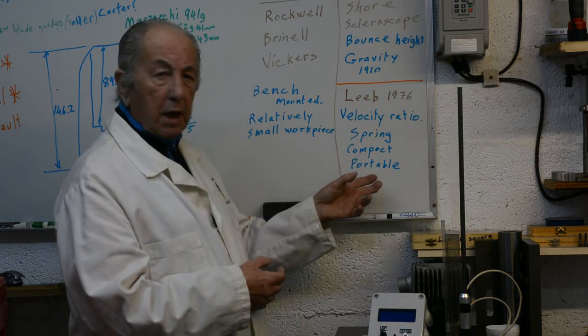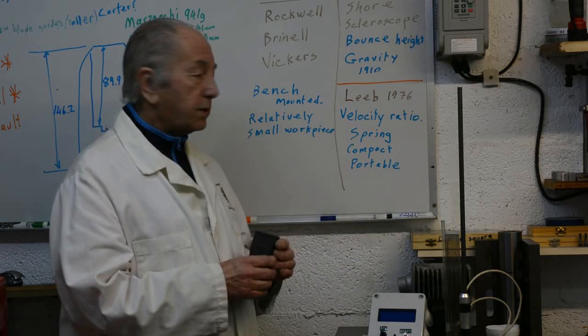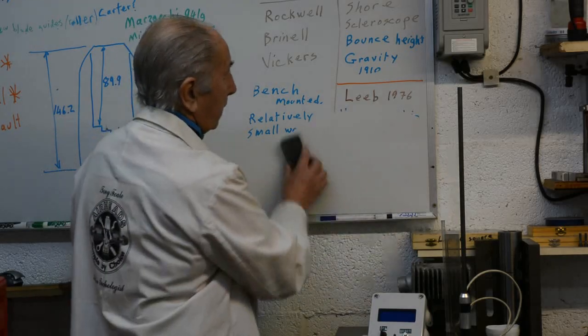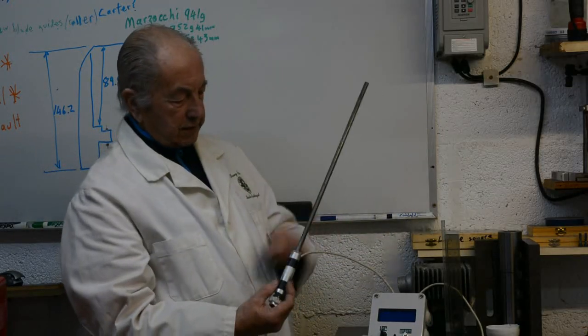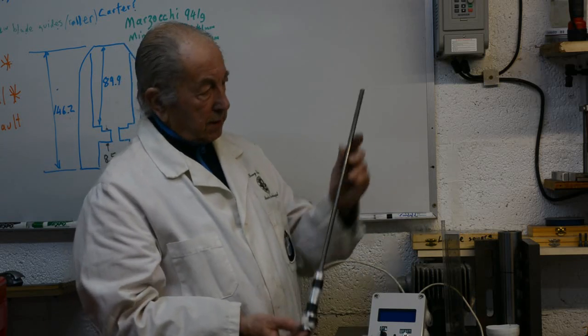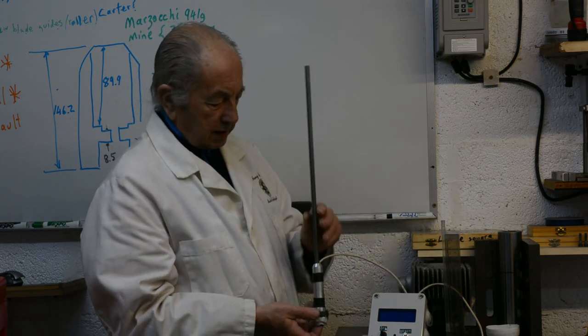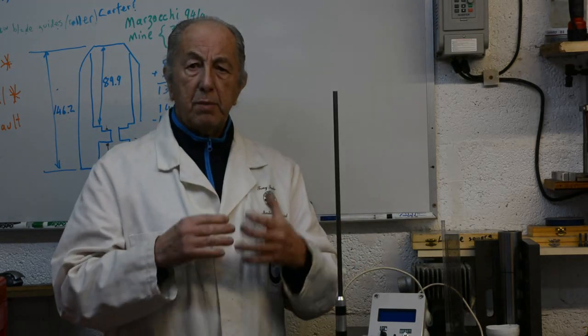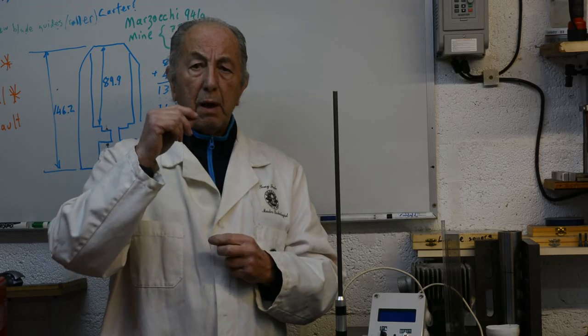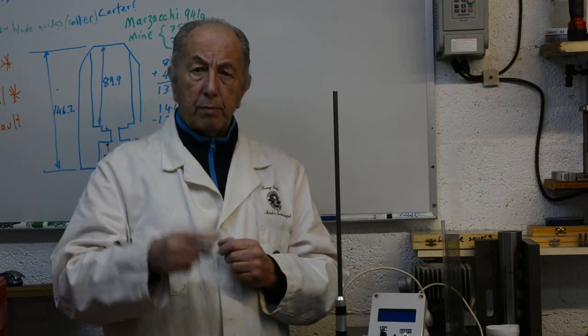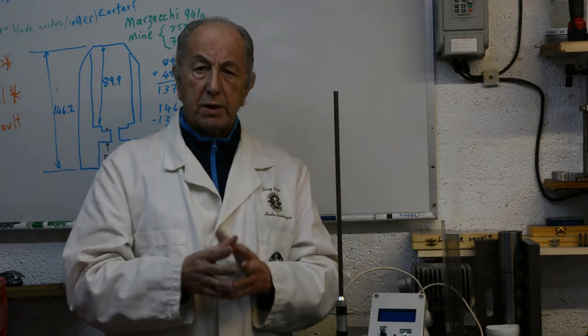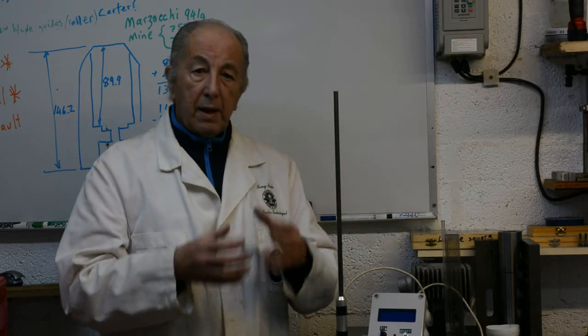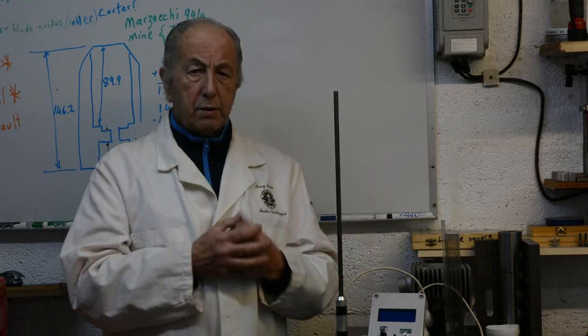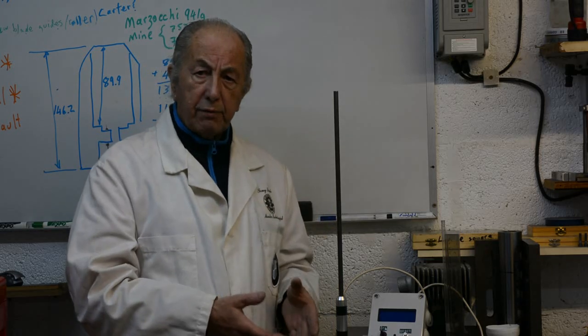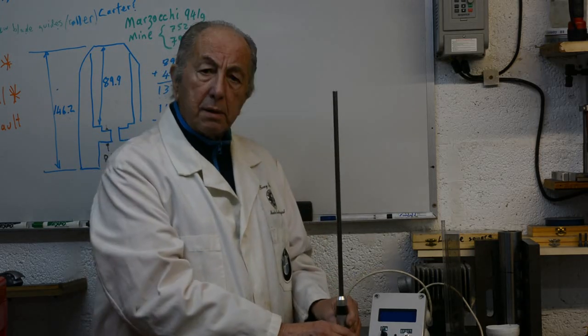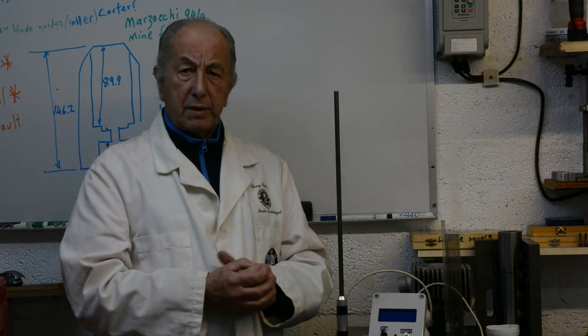Well, for my purposes, I was quite happy to use gravity. Let's look in a little bit more detail as to how I made mine. Well, basically we've seen that I've got a tube. It's a steel tube. It's 1/2 meter long, so the drop distance is 1/2 meter. With the Shore system, because you measured the rebound height, the height from which you dropped the ball was important because that would affect it. By measuring the velocity ratio, as the Leeb did and I proposed, the drop height is not so important. It affects the impact energy of the impactor, but it doesn't affect that ratio of velocities.